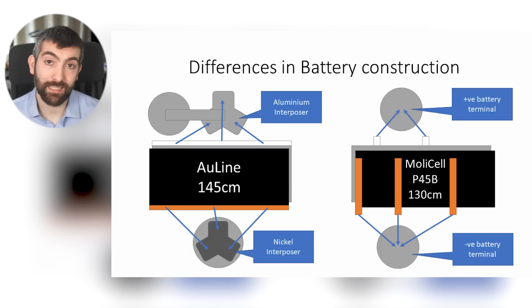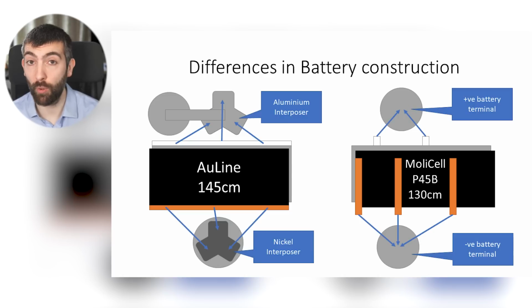They're getting more capacity out of a shorter length of foil, 4,500 milliamp hours rather than 4,000 milliamp hours that we get from the AuLine. And this means the chemistry they're using is probably a chemistry that has more cobalt in it to improve that capacity. That will give them more capacity per centimeter squared of foil, but cobalt is an expensive mineral, so it probably also increases the cost of producing the cell.